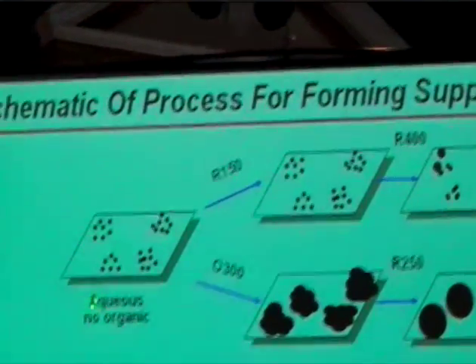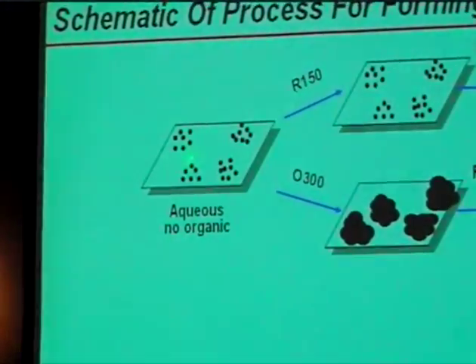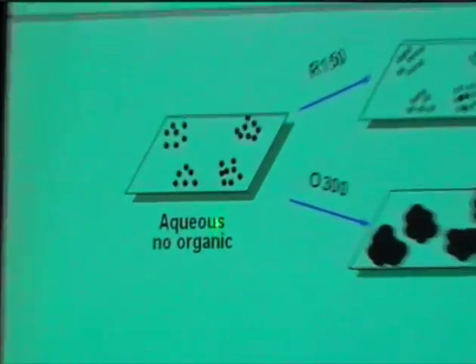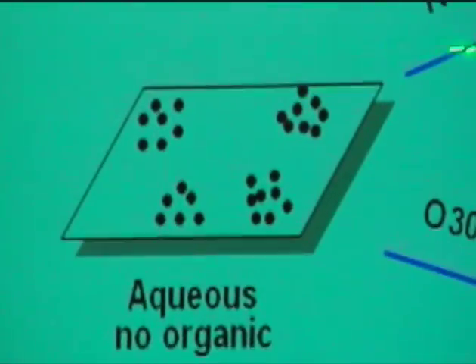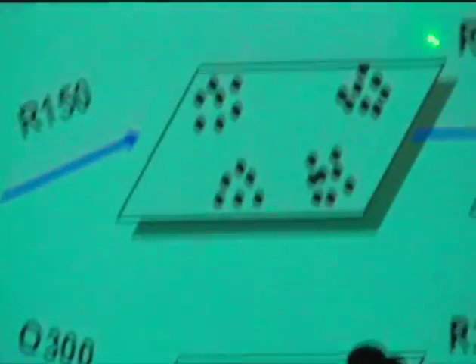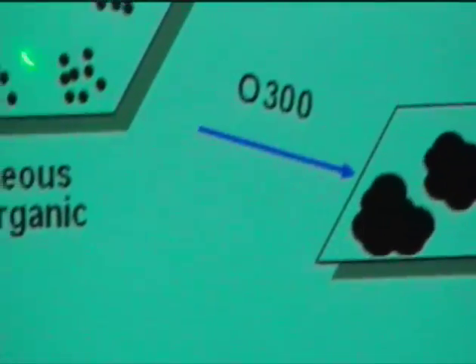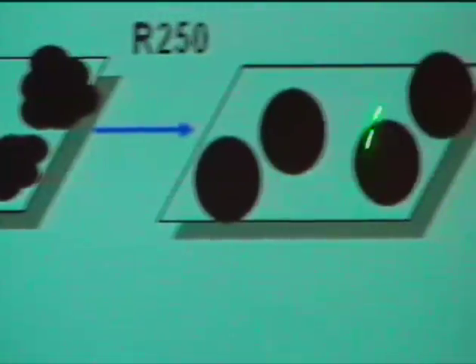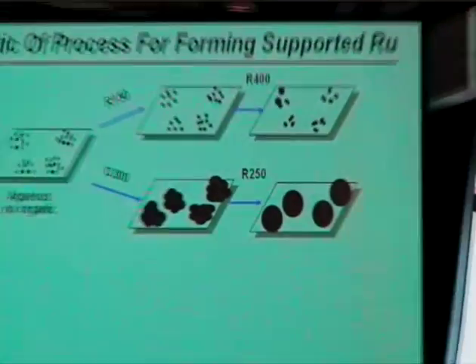And just to summarize pictorially, this is what happens. Aqueous, you do get small crystallites if you reduce it directly at 150, but if you go to 400, some of these things that are close together will reductively sinter. If you oxidize to 300, well, they just become very, very big, and all of them reduce at low temperatures, you get very, very large clumps of ruthenium.